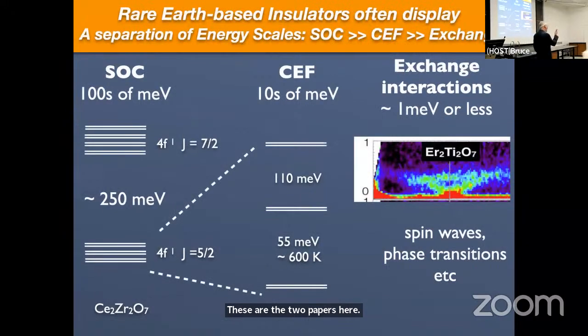Okay, and so now we're going to get to the neutron spectroscopy characterization of this material. And I'm going to show you neutron spectroscopy on 3 different energy scales. And that's often an important thing to do because there are 3 important energy scales in the study of basically any magnetic insulator. Okay, and these are spin orbit coupling, crystal field effects. Okay, and I'm going to explain both of these, and then exchange interactions, which are those interactions that tell you whether the spins want to be parallel to each other, ferromagnetic, or anti-parallel to each other.